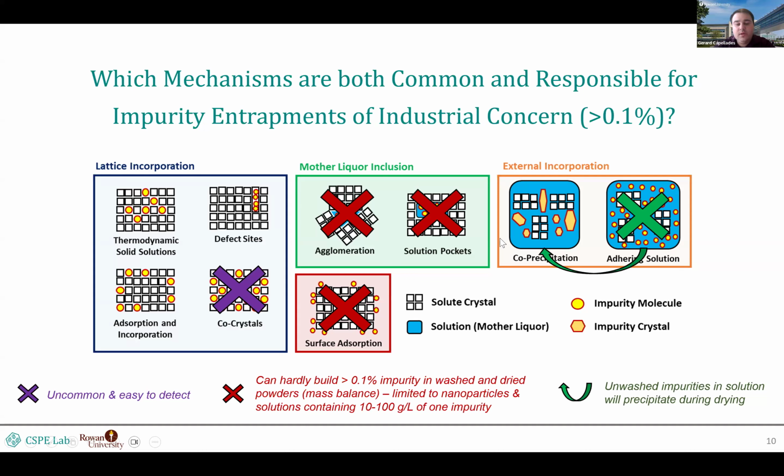of the product, right? And you're left with basically two types of impurity retention, right? One of them is the one where the impurity is basically crashing out on its own. And the other one is a form of lattice incorporation, a form of non-stoichiometric lattice incorporation. Now, in here, we can have some discussions, and I don't want to spend too much time on this, but we could have some discussions about whether the adsorption and incorporation are really just a mechanism to make a solid solution, that the impurity needs to attach to the surface before it can integrate into the lattice, right?